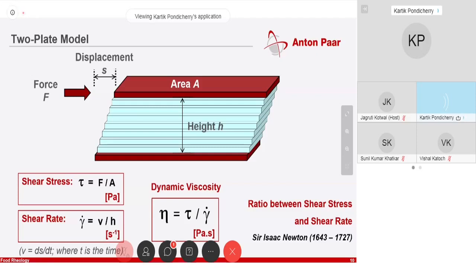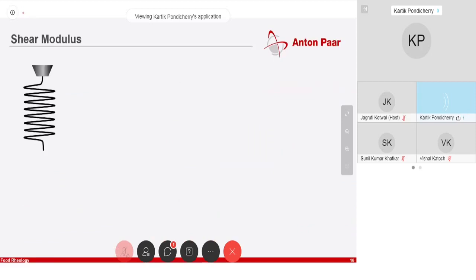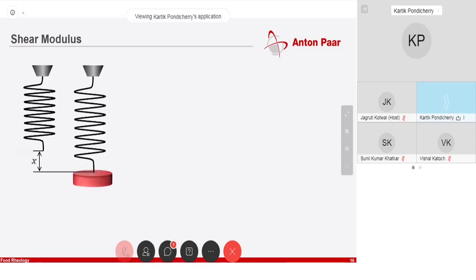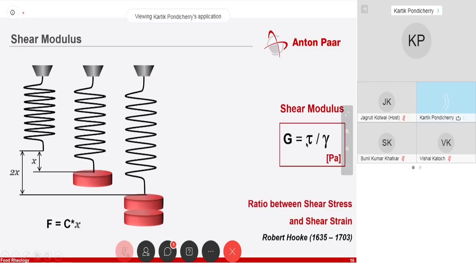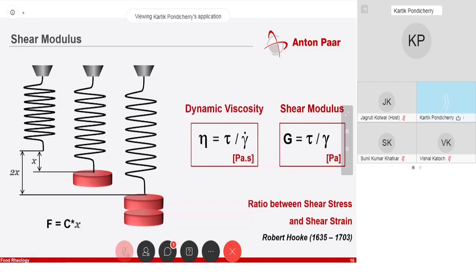Next, viscoelasticity. There you are trying to figure out the viscous part and the elastic part, and we deviate from Newtonian behavior and come onto something called Hookean behavior. It's basic physics — when you have a spring and add a load, you elongate it. Add twice the load and you get twice the elongation, which fits with Hookean behavior: extension is directly proportional to force, and the constant is the spring constant. We apply the same thing for shear, and then the ratio between stress and strain gives you the shear modulus. But still you don't have the division between viscous and elastic patterns — that will come in the next slide.